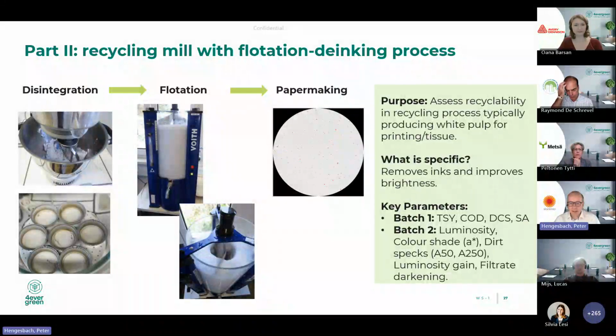And also in those processes, chemicals are typically used to support the release of the ink, which is typical for the flotation deinking process. So this is what you see on the left side. And then the core process for the flotation deinking evaluation is the so-called flotation stage. This is a process where air is injected into this highly diluted pulp, and the air bubbles rise up in this suspension, collecting and removing with the foam on top the ink particles or hydrophobic particles in general.